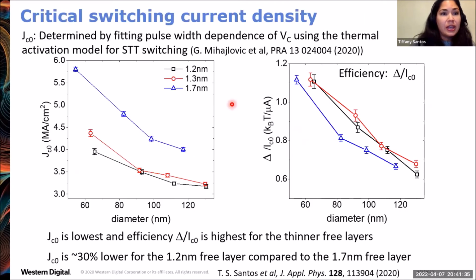Then the critical switching current density we found by fitting the pulse width dependence of the critical voltage using a thermal activation model for spin transfer torque switching. We found that it's the thin free layers that have substantially lower switching current density, by 30% compared to the 1.7 nanometer free layer, the thickest one of the ladder. So then for the figure of merit, the spin transfer torque efficiency, which is defined as the thermal stability factor delta over the critical current, it's the thinnest free layers that have the highest efficiency because they maintain high thermal stability factor, yet at the same time have this low switching current density.